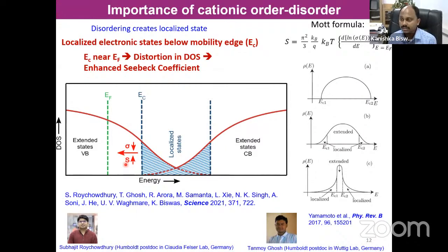weak localization regime. Here we have a partial disorder of atoms, and electrons and holes will have diffusive transport, and this regime is good because we will have a finite amount of electrical conductivity as well as some distortion in the electronic states where we have a good Seebeck coefficient. So we have to work in this weak localization regime. So basically we need to partially order this Ag and Sb. We don't need complete ordering of Ag and Sb. So how do we partially order Ag and Sb?